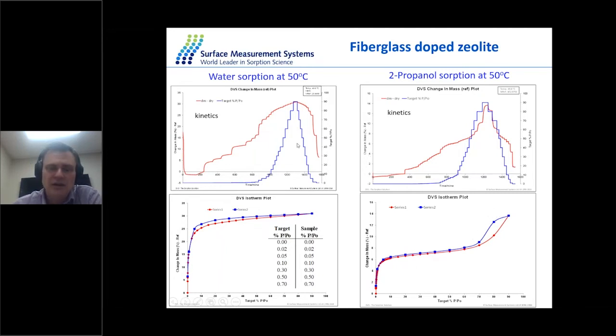Now the same material was used with water vapor. Again, on the top left you have the kinetic plot. Again, we look at very low partial pressures of water. We went down to 0.02 P over P naught.